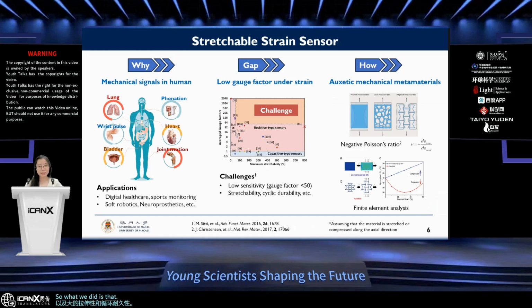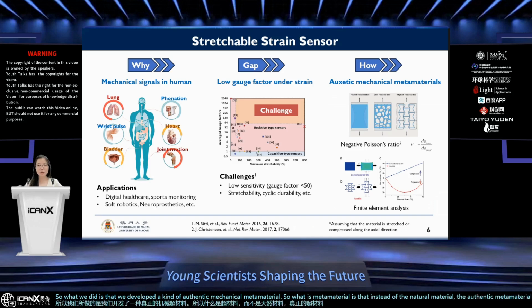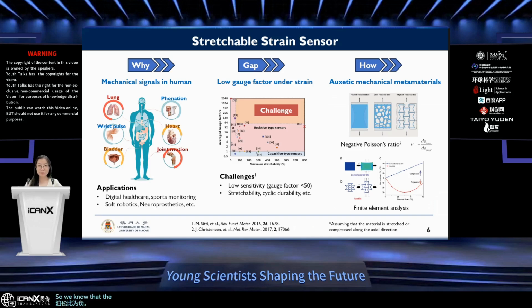So what we did is that we developed a kind of auxetic mechanical metamaterial. What is a metamaterial? Instead of the natural material, the auxetic metamaterial has a negative Poisson's ratio. We know that in nature, incompressible materials such as TPU or PDMS have a Poisson's ratio of about 0.49, which means if you stretch it in one direction, then in the other transverse direction,